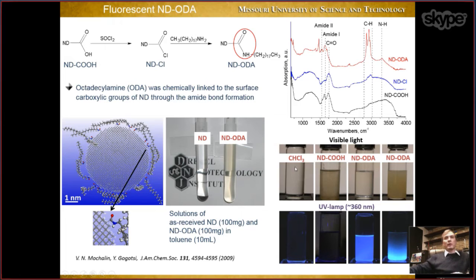So here is pure solvent, which is chloroform in this case, and I try to disperse ND-COOH in chloroform. It doesn't like it, it doesn't disperse. You can see it sticks to the walls, it forms agglomerates in solution. You will see particles there if you look closer. So it doesn't disperse, and it shows no fluorescence.